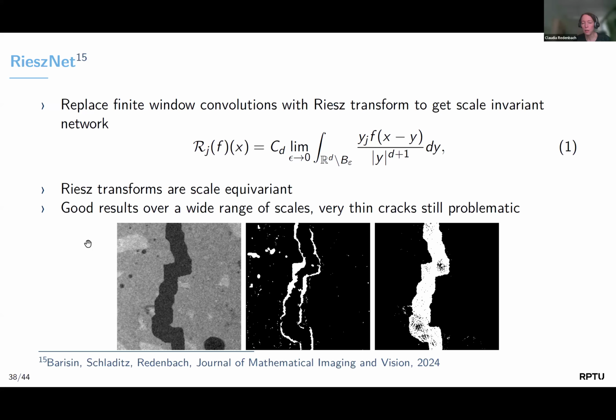So if we take a network trained on fixed crack thickness, so for instance, 3 pixel thick cracks, if we use a standard UNet, it would basically just find the boundary of the cracks because it wouldn't expect such thick, dark regions and wouldn't consider them as cracks. The Riesz network, on the other hand, does have the capability to generalize, so that would find cracks of very varying thickness, even if trained on fixed scales.